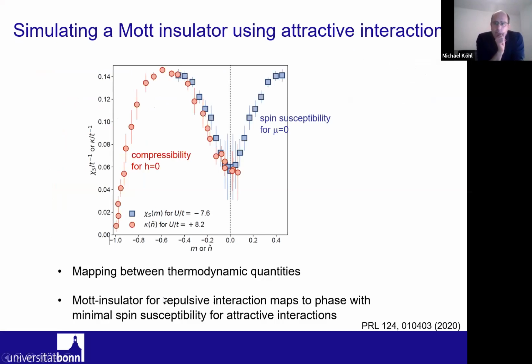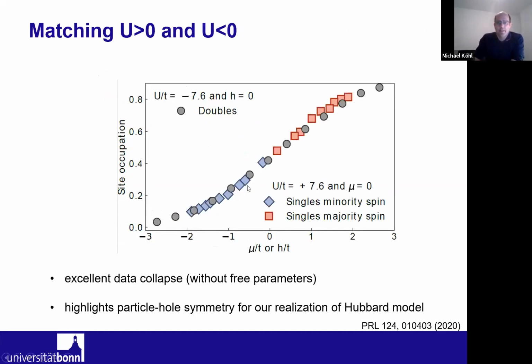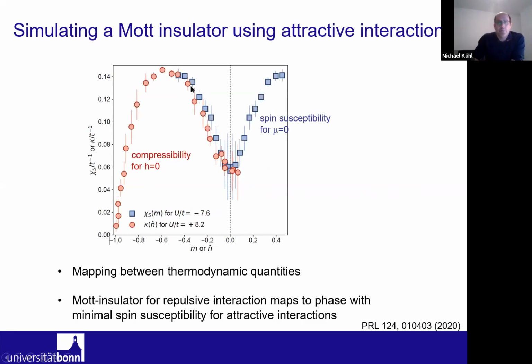And now we can take this one step further and ask, so we see that the density is precisely mapped between repulsive and attractive interactions if we swap chemical potential and Zeeman fields. But does this also apply to other thermodynamic variables? And here we show this now for the compressibility. So for the repulsively interacting gas, we know that we have a minimum of compressibility when we enter the Mott insulator phase. And we measure the compressibility simply by taking the derivative of the density with respect to the chemical potential. So it's basically the slope of this line provides us with the compressibility. And that is shown as the red data points here. Again, everything is just scaled in the tunneling matrix elements. There are no free parameters in this.